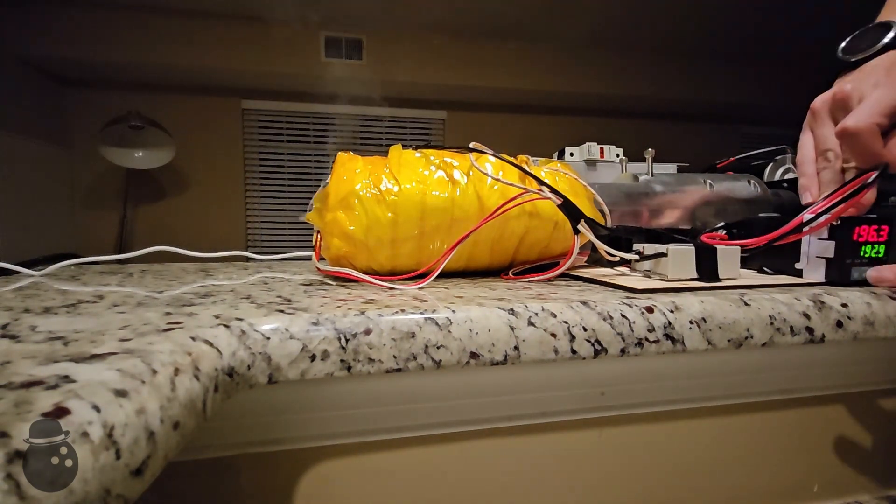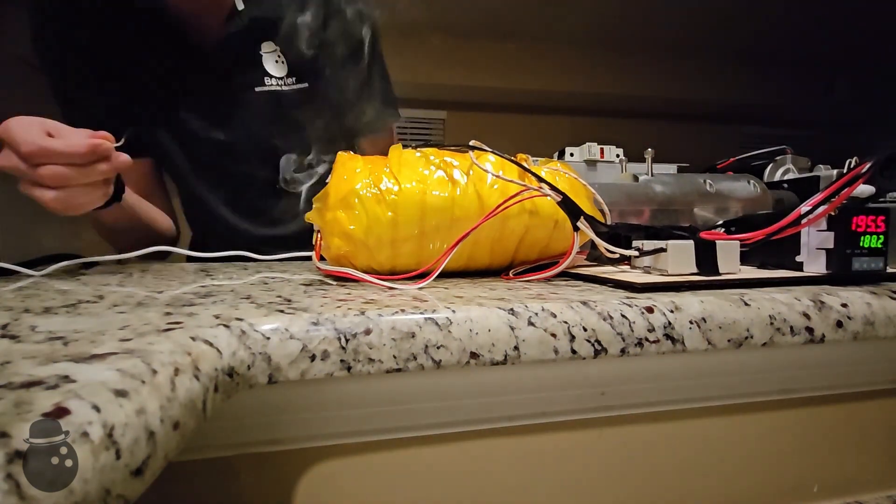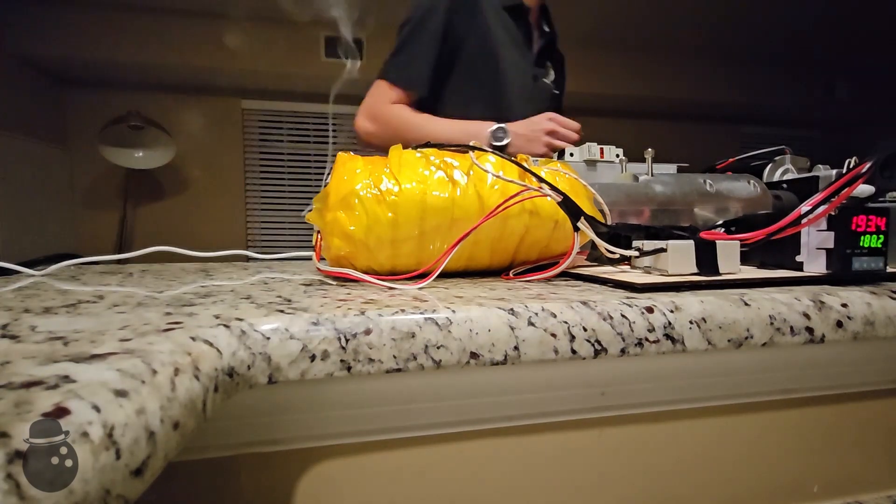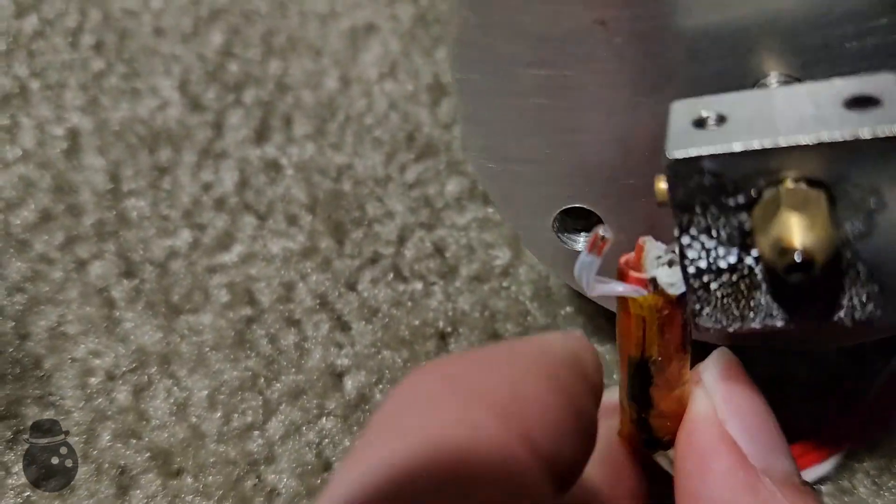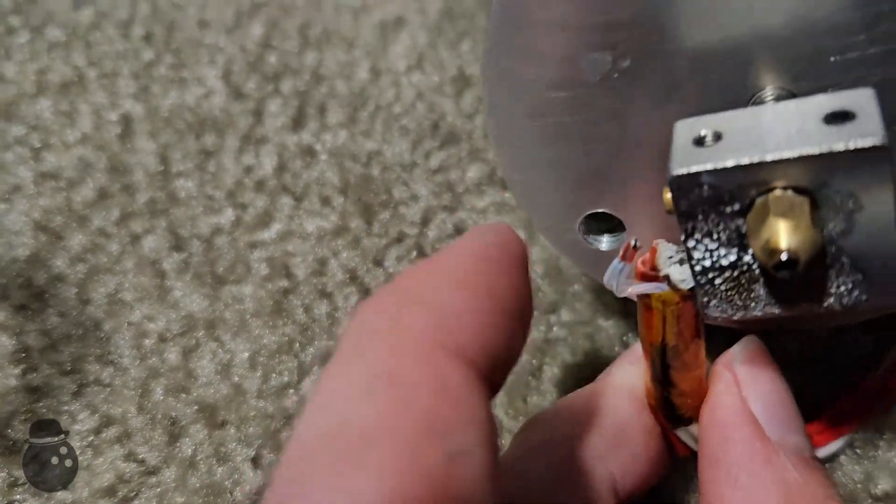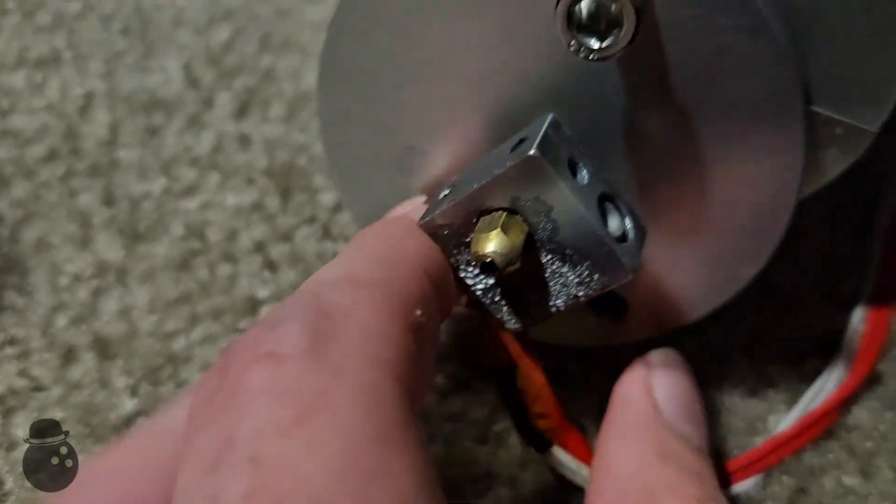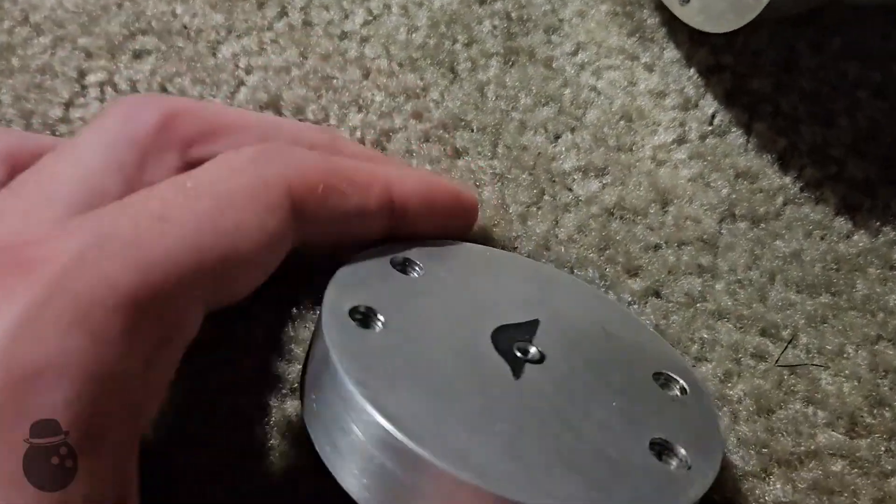I eventually realized it was probably clogged in the nozzle, so I tried to clear the jam with paperclip, which only burned me considerably. The next day, after it had cooled down, a post-mortem revealed that the thermocouple to the secondary heater came loose and likely caused the heater to rail at max power, endlessly confused as to why it wasn't getting hotter, which caused it to cook the filament into likely toxic fumes.